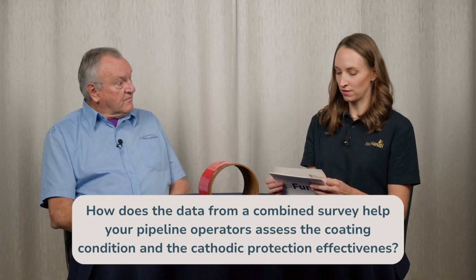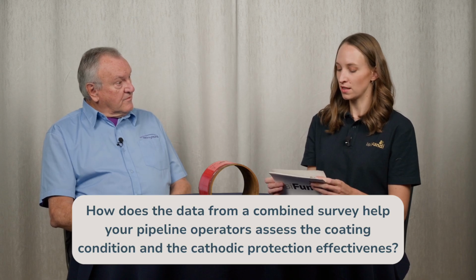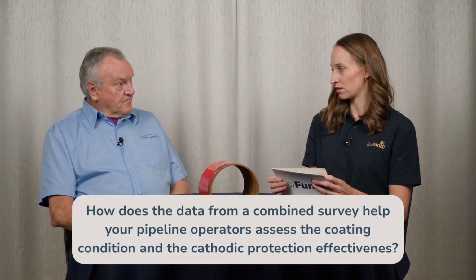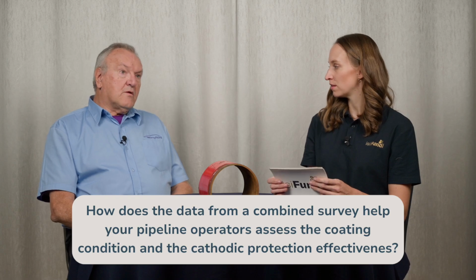Yes. Perfect. Now, how does the data from a combined survey help your pipeline operators assess the coating condition and the cathodic protection effectiveness at once? Well, the data analysis is done after the survey. Okay. So you go over the pipeline route, you gather all the data, go back to the office, and you post-process. And that data is then linked to the position of the survey team, where it was.